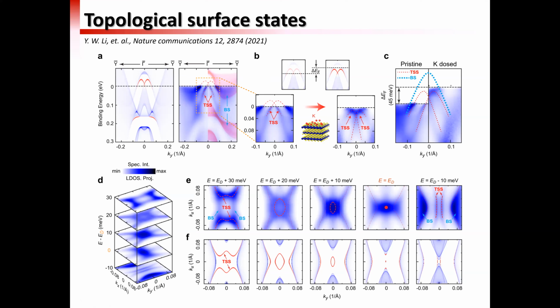So in order to see this Dirac point, we carry out a trick which is typically used by ARPES people: we just dope some potassium on top of it. The potassium will donate some electrons and lift the Fermi level. And indeed, you see that after this doping, the whole band sinks a little bit, and we can see the crossing of the topological surface state and also the Dirac point. On the right-hand side, on the top row, you can see the comparison between the pristine sample and the potassium-doped sample. The Fermi level was lifted by about 45 meV. Then we can see the whole branch of this topological surface state.